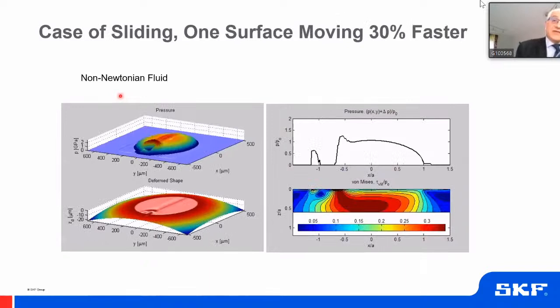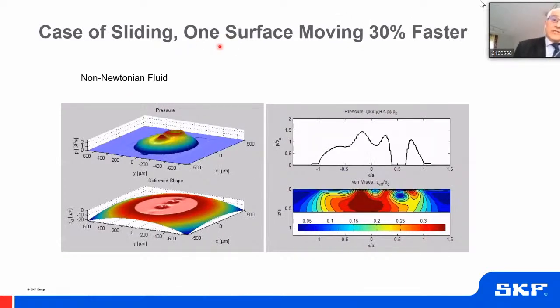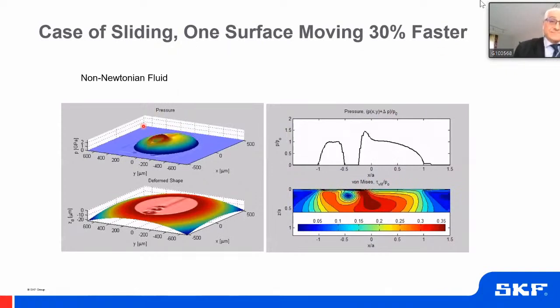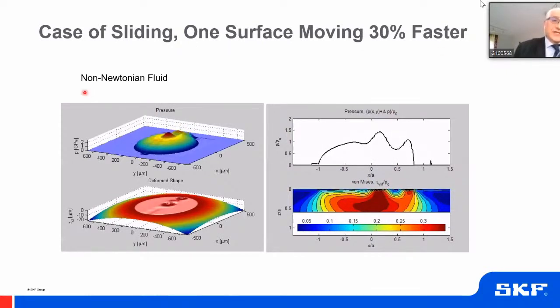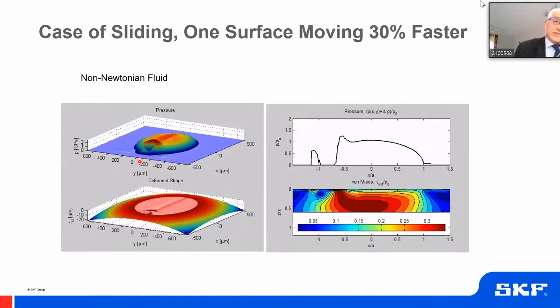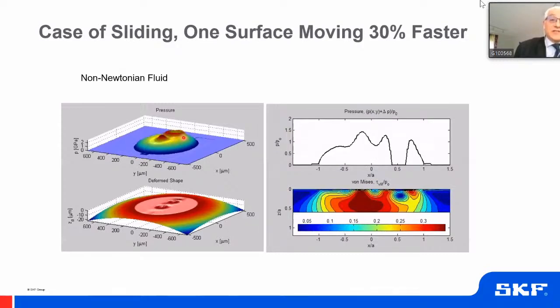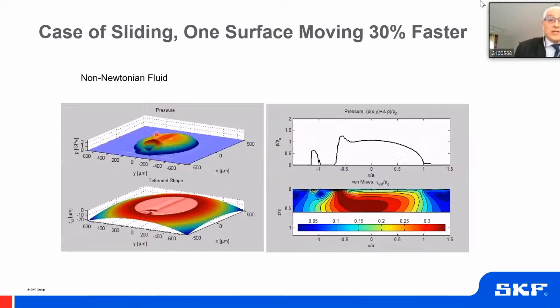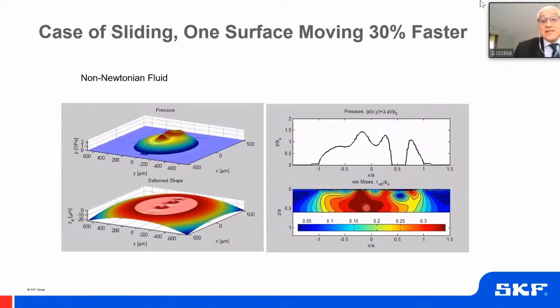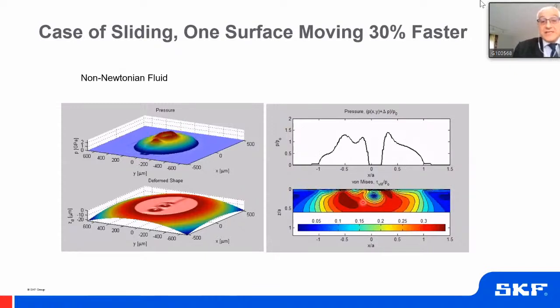The same problem, but now with an indented surface that is moving 30% faster than the smooth surface, with a non-Newtonian fluid. You see immediately how the two waves separate because they travel at different speeds. So the indentation has already left the contact while the ripple is still inside the contact. And that has important consequences in fatigue as well.